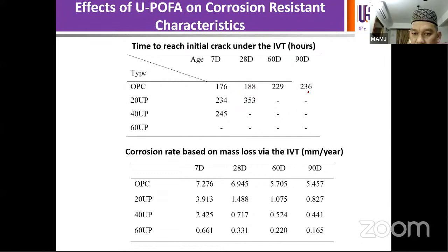crack was observed. All right, and calculation of corrosion rate based on mass loss through the IVT in millimeter per year, there is a significant reduction in the corrosion rate based on this technique in comparison to the one in the control OPC concrete. All right.